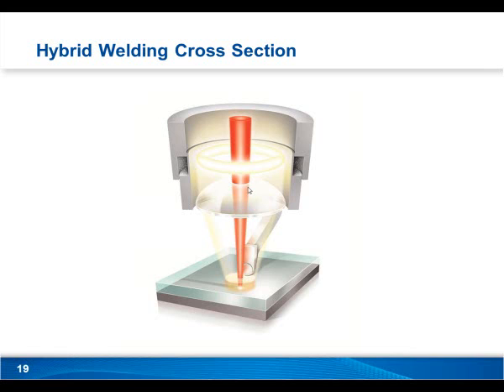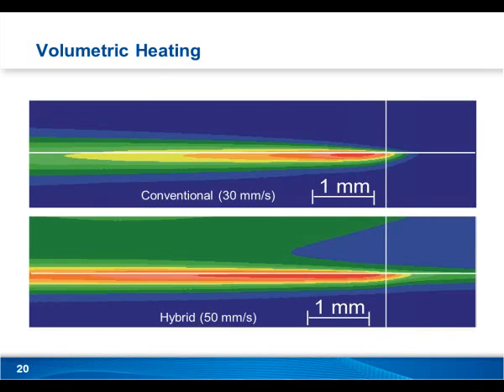But by adding the halogen radiation, the polychromatic radiation, we're able to volumetrically heat the upper layer as well. And so what this is going to do is we're essentially preheating the plastic. We're creating a larger welding zone outside of just the laser. So you can see here, here's the difference between regular, this is conventional contour welding, and then hybrid welding. This white line in the middle is the interface between the two parts. And so you can see the amount of added heating in the upper layer here.